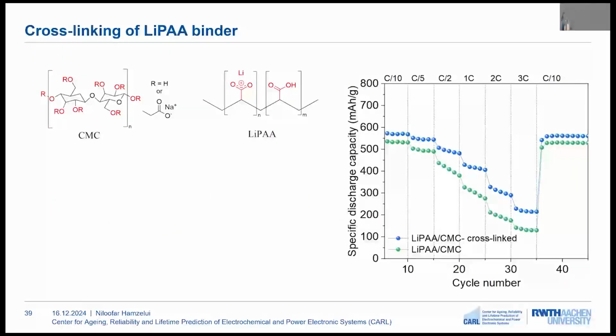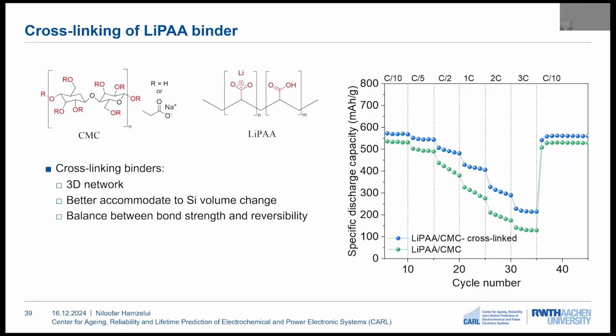Then the cross-linking of a lithium polyacrylic acid binder was investigated with carboxymethyl cellulose. So here in this image, we can see the rate capability of cells with the cross-linked and uncross-linked binders using LiPAA and CMC. And in terms of cross-linking the binder, we can form a 3D network, which can better accommodate to the volume change of the silicon. And it can also bring a balance between the strength and reversibility. At lower C rates, we can see more similar performance of these electrodes, but at higher C rates, we can see up to 60% capacity enhancement in case of cross-linking the LiPAA binder with CMC.